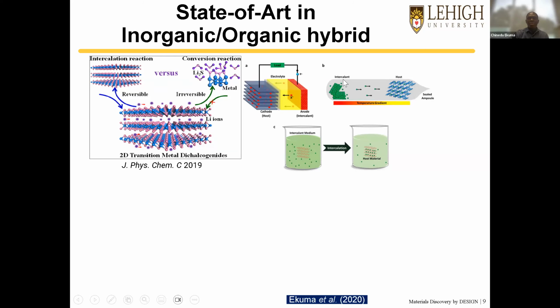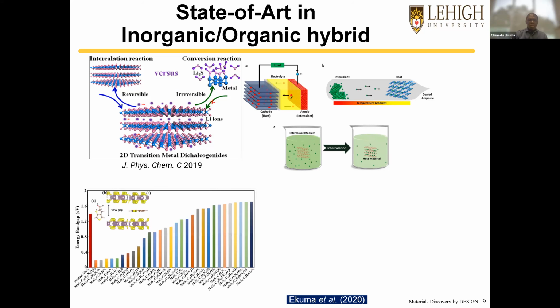There are many ways. This is a couple of ways that we can do the intercalation. It can be by electrolyte, electrochemical, either chemical, or a scenario whereby you put the intercalant and the host between a sealed environment and run some temperature gradient across them that makes them mix naturally. Now, what we are saying is, instead of putting lithium, sodium, or elements between these naturally occurring van der Waals gaps, we can put molecules. Specifically, we've been interested in conjugated molecules, small conjugated molecules, and organometallic molecules. So we can put it in between these layers. And you should be able to tune their properties.